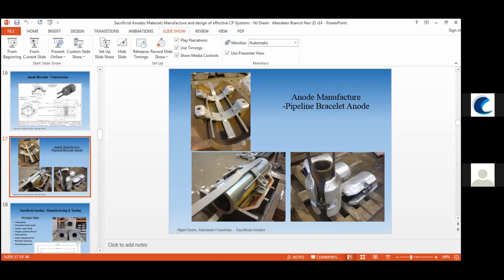On these materials, we put epoxy and things on the inside of the anode materials, mainly to stop the loss of material on the inside, which is adjacent to the strap, which is retaining the aluminium which is cast onto it. So we prevent loss from the inside.